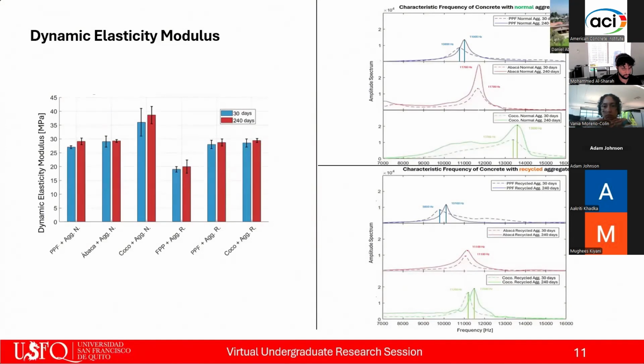Over time, resonance peaks also became more symmetrical, suggesting improved internal structural stability. However, mixes with coconut fibers showed the greatest variability due to workability issues. Fibers tended to clump, creating heterogeneity. This was visible in the Fourier transform results, where the peaks were more irregular from as early as 30 days.